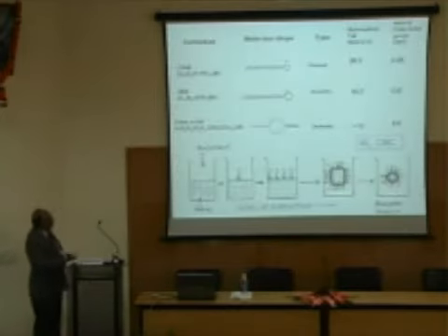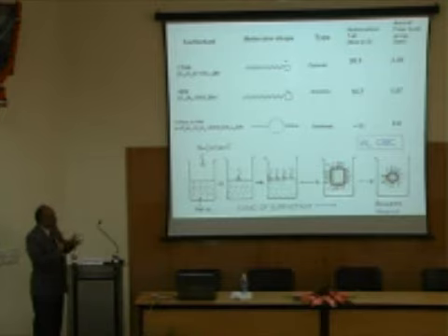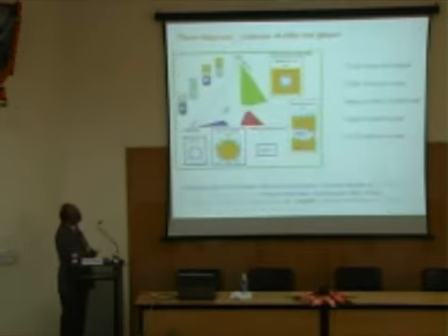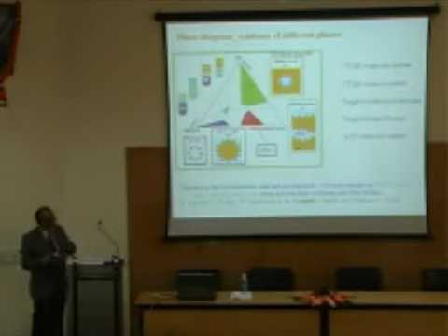So, if you keep adding these surfactants, if you add less surfactant, they hang on to the surface. Beyond a certain concentration, they start reorganizing among themselves, okay? And they form spherical micelles. So, this particular number which you reach, after which it becomes like this, is called the critical micellar concentration, which is a very important parameter when you do synthesis. And you have to know that you have several parameters now. Oil is there, surfactant is there, water is there.